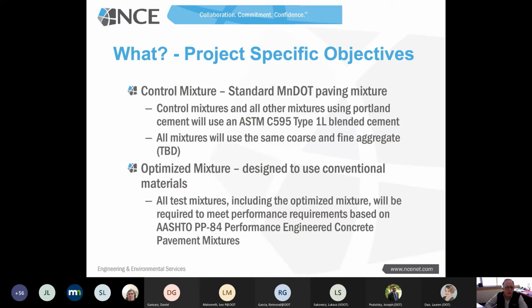All of the materials are going to be required to be processed through a conventional ready mix operation and placed using a slip form paver. So that applies to all mixtures we're looking at in this study. The optimized mixture is taking advantage of some things that have been developed and have been gathered in a new document, AASHTO PP84, Performance Engineered Concrete Pavement Mixtures.